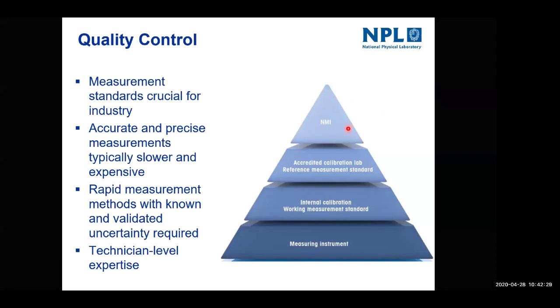And then you can use those techniques to validate your fast quality control procedure at the bottom here. Again, that could be something like Raman spectroscopy. It could be something, as I talked about, like your BET or XRD, techniques that are bulk techniques, and again, they're not necessarily as fast as an optical technique, but they're not as slow as, say, a microscopy technique. Again, as long as you understand what the change means in these values that you get from those techniques, and you can quantify it by validating it off of the top of these very accurate, precise, but expensive and time-consuming techniques. This is really important. There's a few examples there of different techniques that people do use for quality control to try and help them understand that. But they're not the only ones.